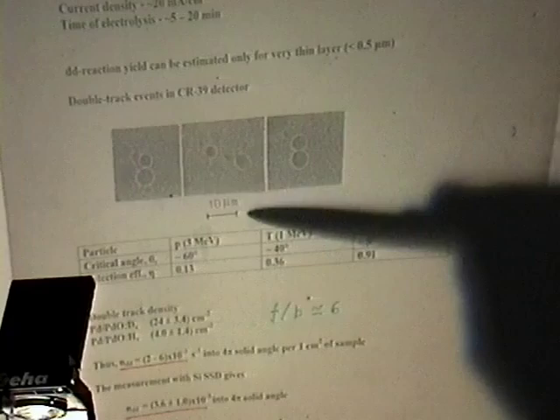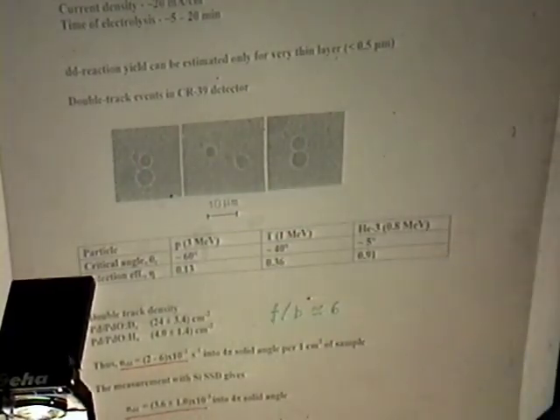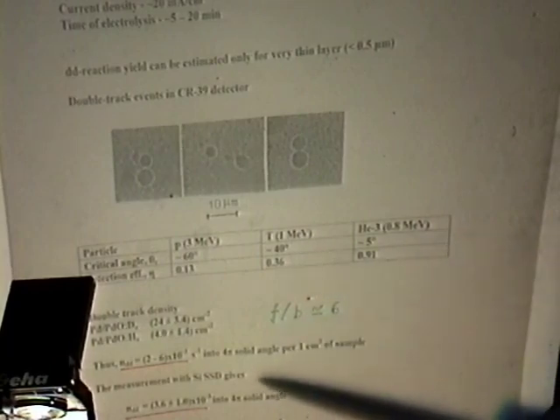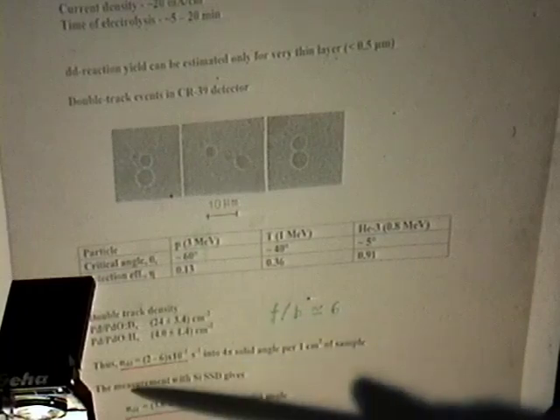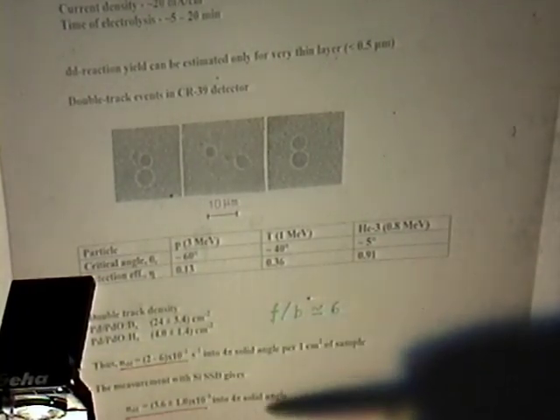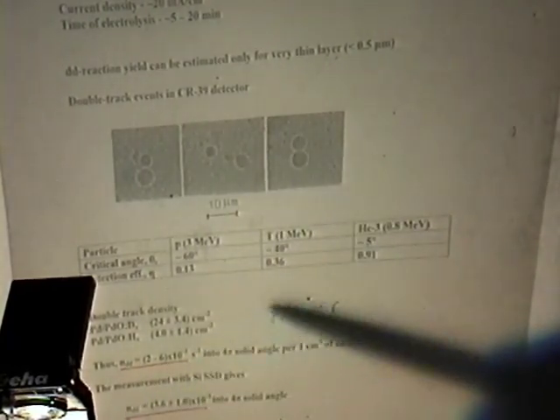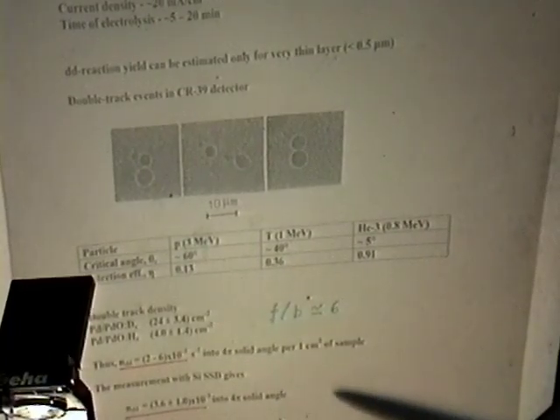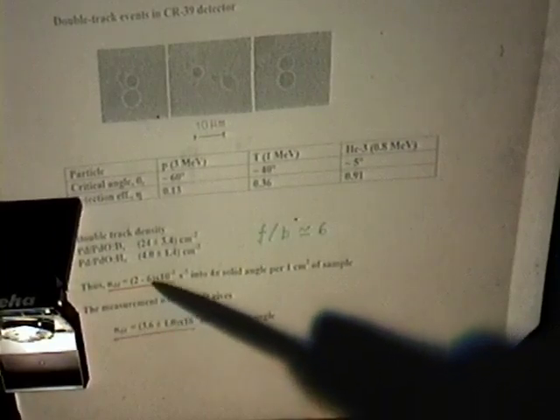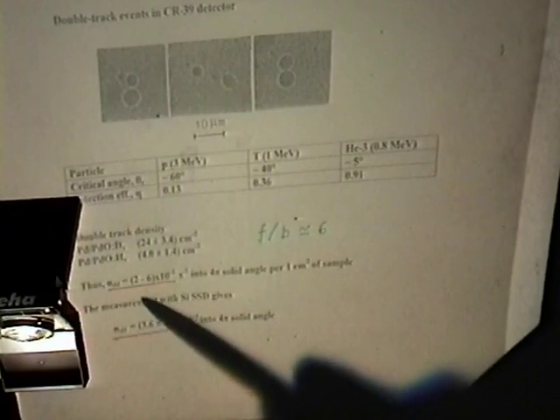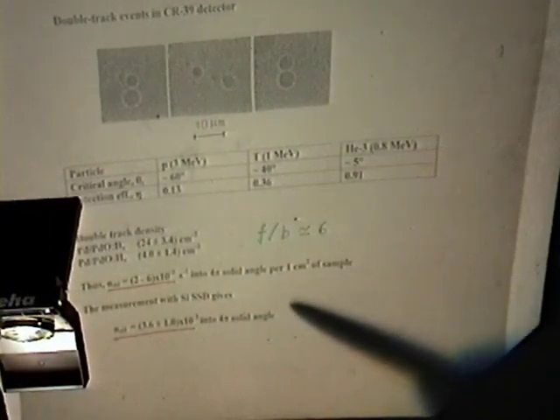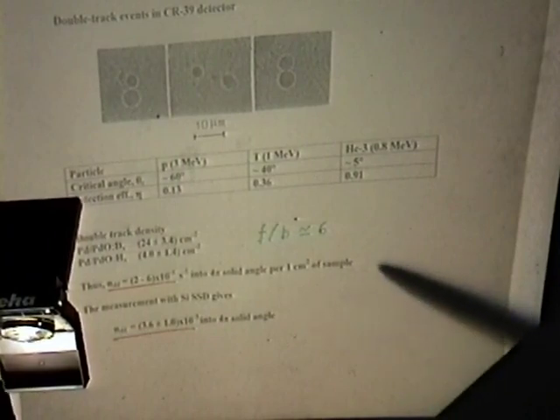And to estimate the detection efficiency of this double coincidence, we used the hydrogenated samples as a background. In the background measurement and in this experiment, we have a foreground to background ratio near 6. According to this calibration, we estimate the deuterium yield as from 2 to 6 times 10 to the -3 per second into 4π solid angle per 1 square centimeter of sample.